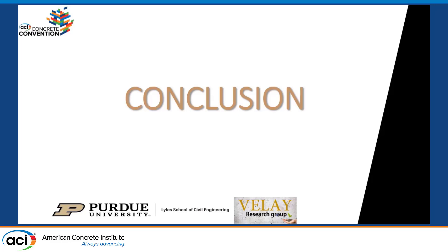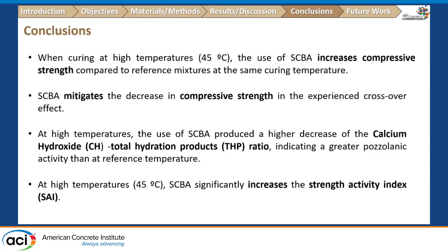In conclusion, our preliminary results show that at high-temperature curing, the ash increases compressive strength. Regarding the crossover effect, the ash mitigates the decrease in compressive strength observed. Additionally, at higher curing temperatures, the ash demonstrates greater pozzolanic activity, and we see an increase in the strength activity index.